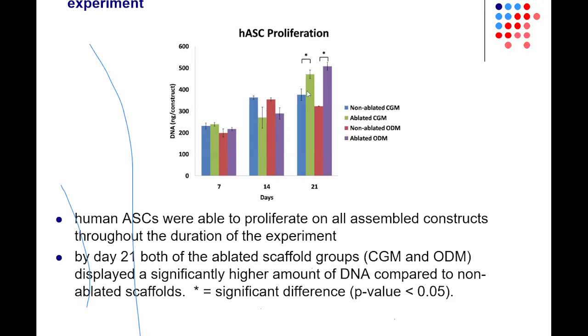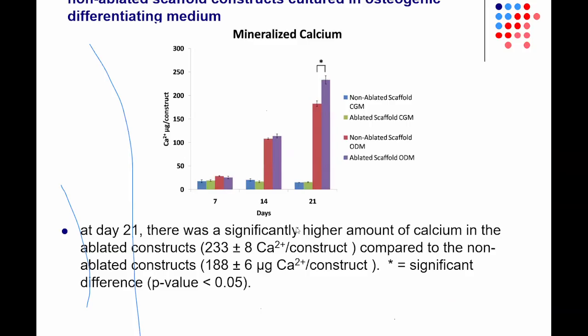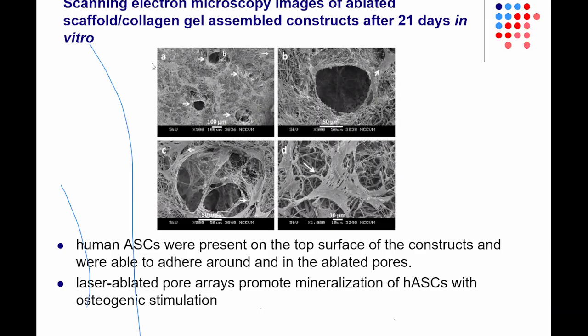You have a much higher amount of DNA within these porous scaffolds than within the non-porous scaffolds. You can also see much higher amounts of mineralized calcium within these porous scaffolds, when you are growing these adipose-derived stem cells in osteogenic differentiation. So you're trying to push these adipose-derived stem cells to behave like bone-forming cells. When you do that, you're getting high amounts of mineralized calcium in these porous scaffolds versus the non-porous scaffolds. There's a good amount of adipose-derived stem cells that have seeded these porous scaffolds and have essentially high-level proliferation within these scaffolds.